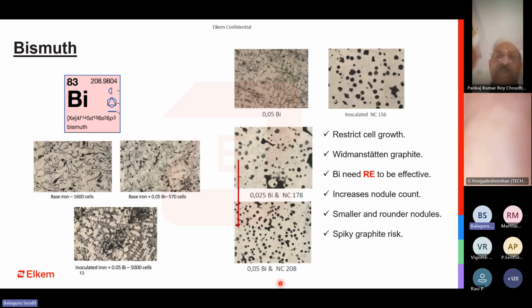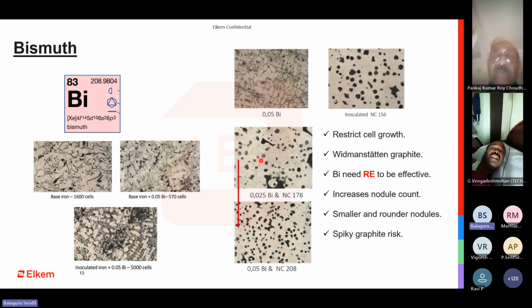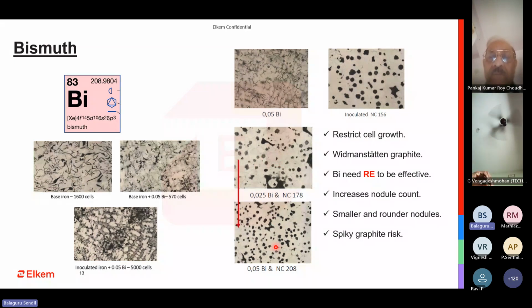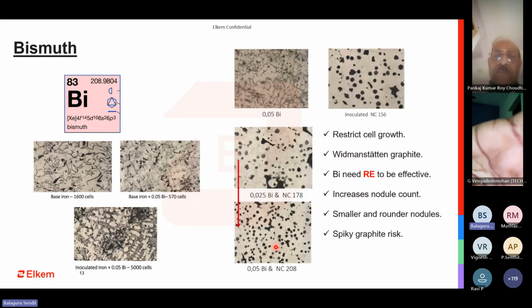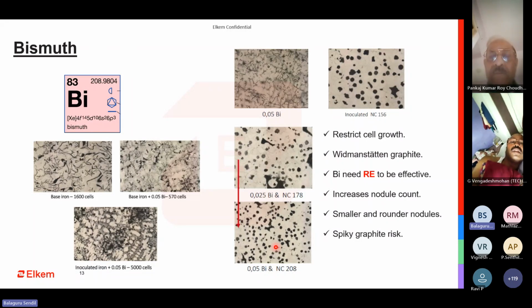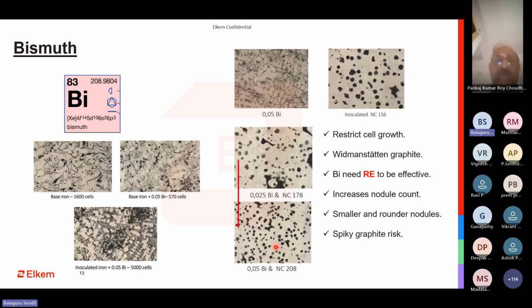So it kind of breaks up the big nodules into smaller ones, and then you have more nodule count, and the average size of the nodule comes down by about 10 to 15 microns. So these are the advantages of having bismuth, but the drawback here is that bismuth alone cannot do this. It definitely needs rare earth to be effective. The mechanism in which it works is quite complex. We have much better understanding of that in Elkem. That's another separate topic we can discuss forward.